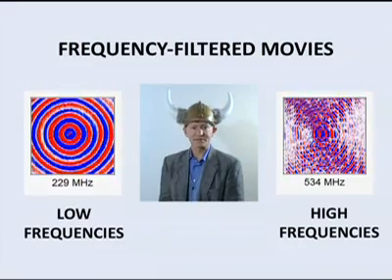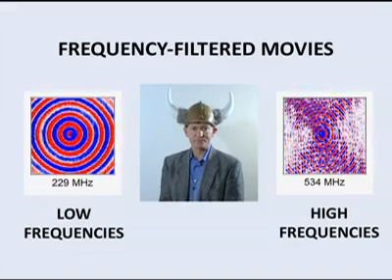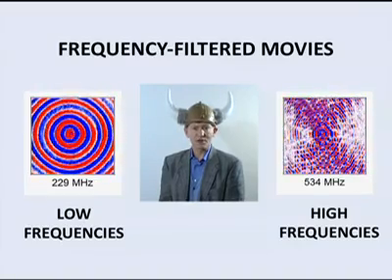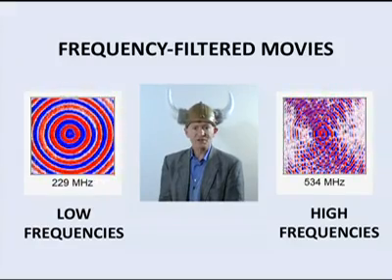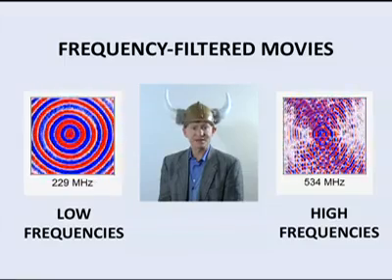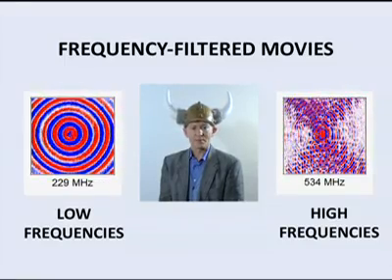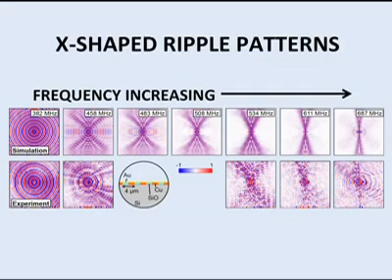Let's analyse at different frequencies. At low frequencies, we see roughly circular ripples. This is reasonable, because the sound wavelength is about 10 microns, much larger than the grating bars, so the sound effectively doesn't see the grating. But at high frequencies, we see this interesting X-shaped pattern, and the X shape closes at higher frequencies. The top row shows that we can get the same effect with numerical simulations; the bottom row is the experiment.